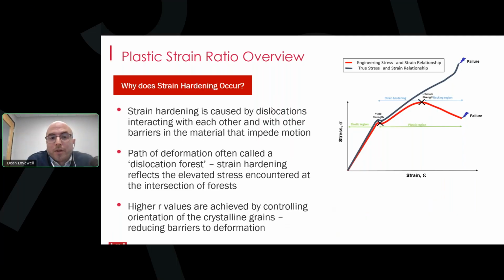As you could guess from its name, the plastic strain ratio is determined during the strain hardened region of the stress strain plot. During this part of the test, dislocations within the metal are moving. And as they move, new dislocations are being generated. Now, the rate at which a metal can create and store dislocations, and thus the extent to which it can strain harden, is directly dependent on its microstructure, which is in itself dependent on the composition.